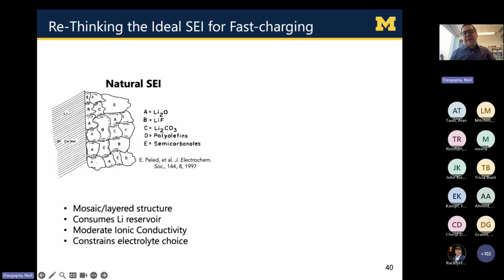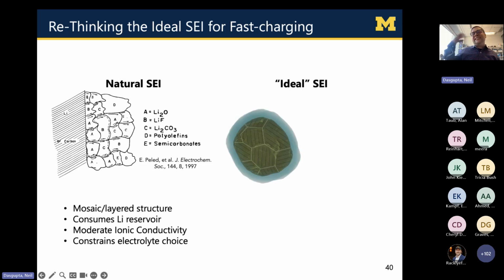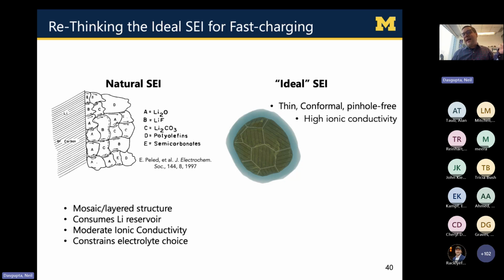This is something we've known for many years. It's actually a quite complex composite material that has many different phases of organic and inorganic constituents. So we asked ourselves, okay, what is the ideal SEI layer and how might that influence fast charging? We thought really we'd like to make an SEI, if we're going to make an artificial one, as I'll show you in a moment with coatings, that's thin, conformal, pinhole free. It's got to have a high ionic conductivity for lithium to go in and out. It must be electronically insulating. And the key point is homogeneous. We'd like to get rid of all that heterogeneity of these different phases within the SEI. And by the way, it must also be stable at these very low voltages.